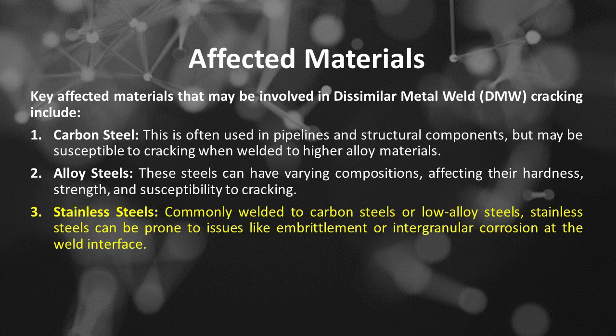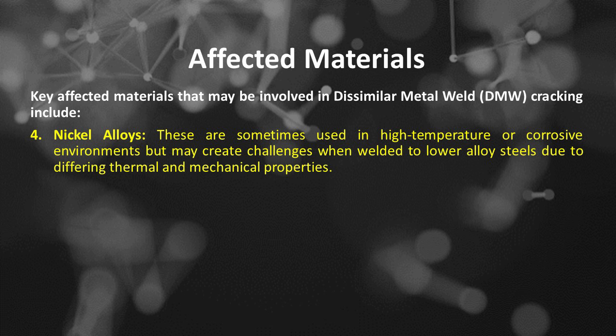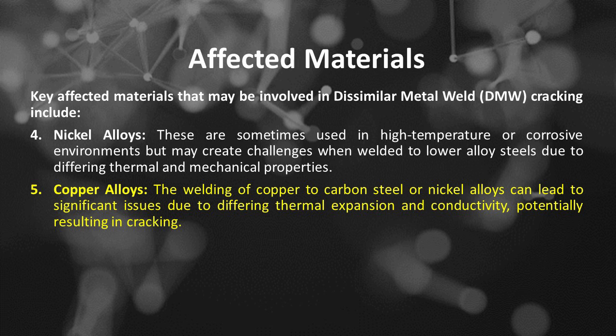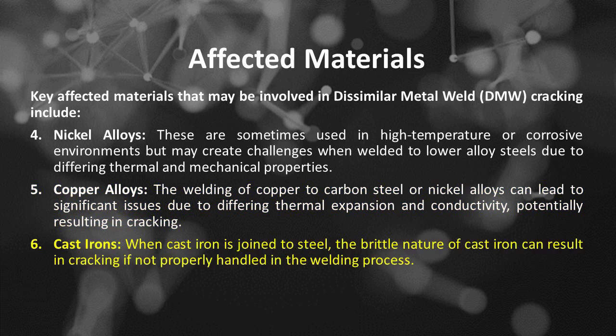Number 4 is nickel alloys. These are sometimes used in high-temperature or corrosive environments but may create challenges when welded to lower alloy steels due to differing thermal and mechanical properties. Number 5 is copper alloys. The welding of copper to carbon steel or nickel alloys can lead to significant issues due to differing thermal expansion and conductivity, potentially resulting in cracking. Number 6 is cast irons. When cast iron is joined to steel, the brittle nature of cast iron can result in cracking if not properly handled in the welding process.